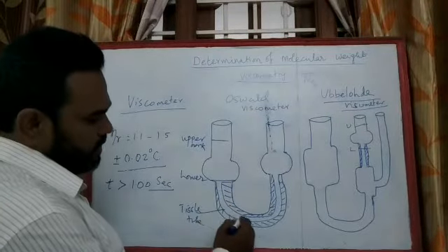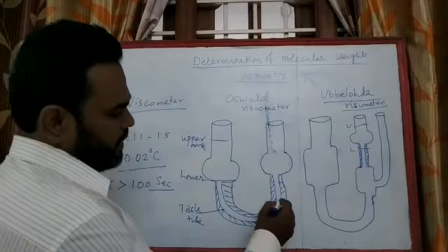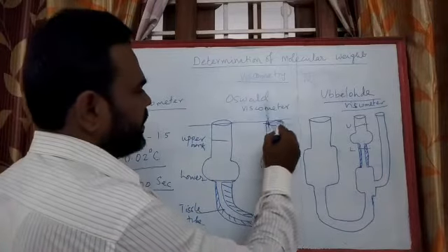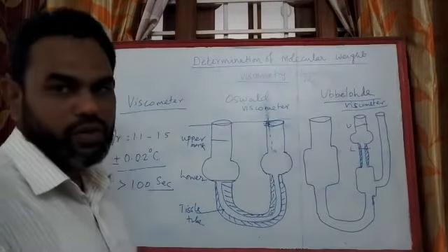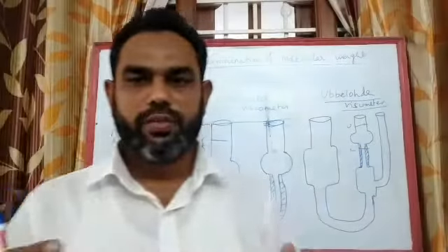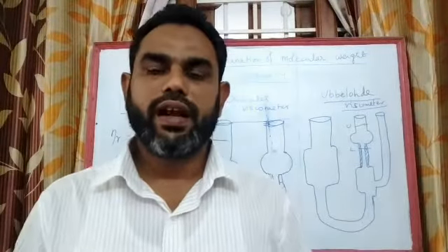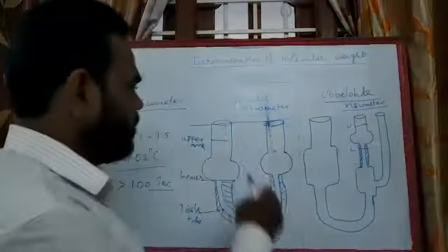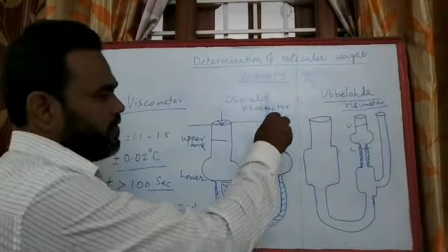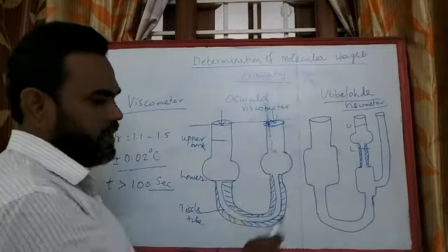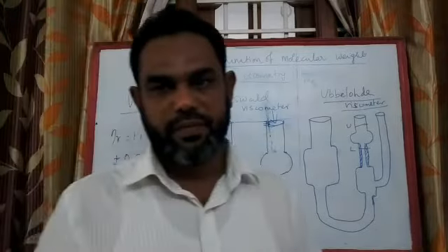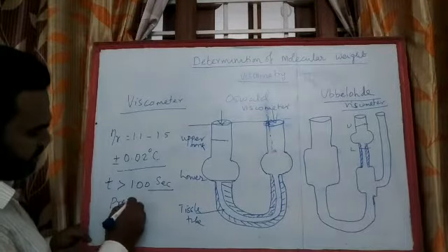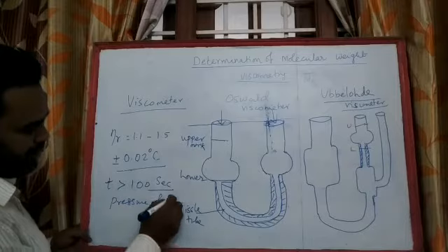Okay, then the viscometer consists of a fine capillary. And the pressure head should always be equal throughout the measurement. The viscometer should be kept perfectly vertical. Otherwise, what happens? The pressure head on the viscometer bulb will vary. So the variation of the pressure head leads to errors in the measurement. Okay, so this is the next precaution. The pressure head should be maintained.